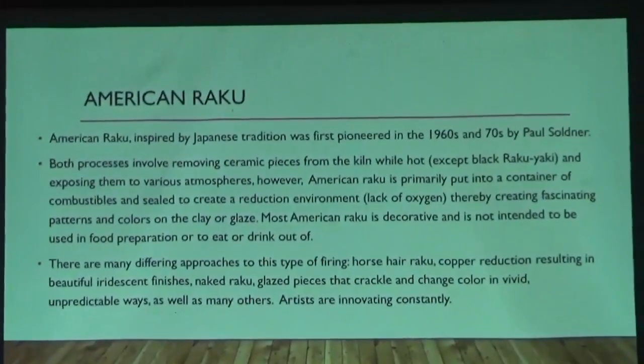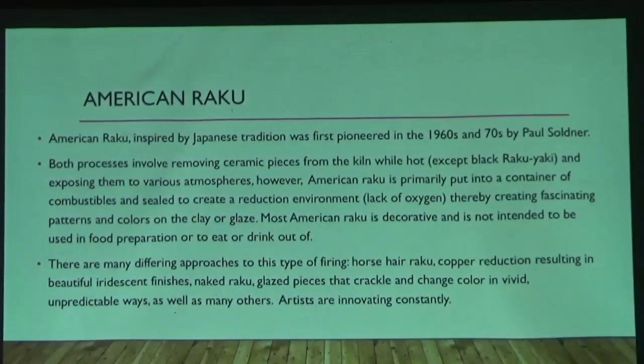So they're wheel thrown, they're bisque fired, which is the first stage of firing, where you take it from just raw clay and you're actually starting the process of turning it to stone, something a bit more permanent. At that point, it's heated to about cone 04, roughly 1950 degrees Fahrenheit, and let cool for about a day, just so that it can recapitulate, kind of strengthen itself, and become stone, because after that, it goes through a real trial by fire, no pun intended, maybe a little bit.